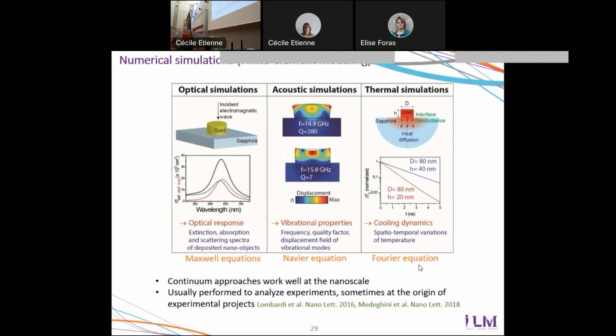So we can extract absorption and scattering spectra by numerically solving Maxwell equations. We also perform acoustic simulations, so that's for the vibrational part of our studies. With these simulations, we can see what the vibrational modes of an object look like, and we also have access to their frequencies and quality factors. I will show examples of it in the next part.